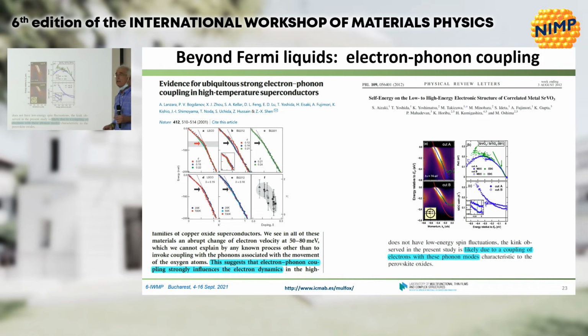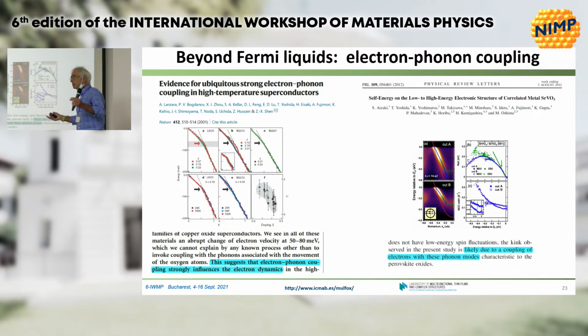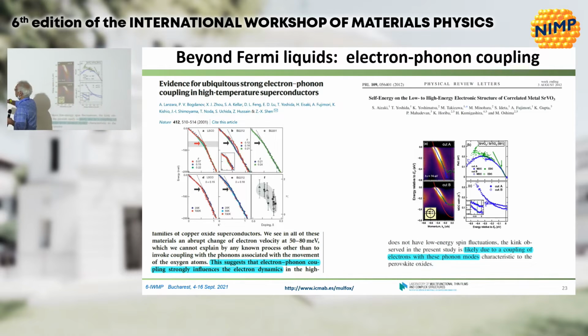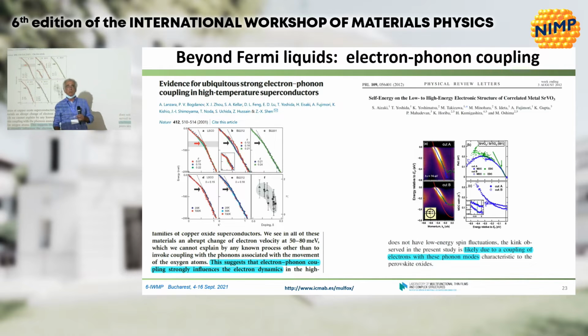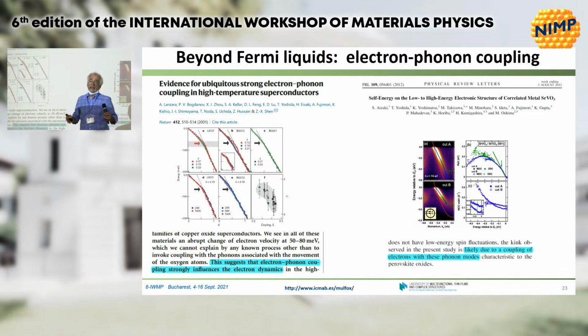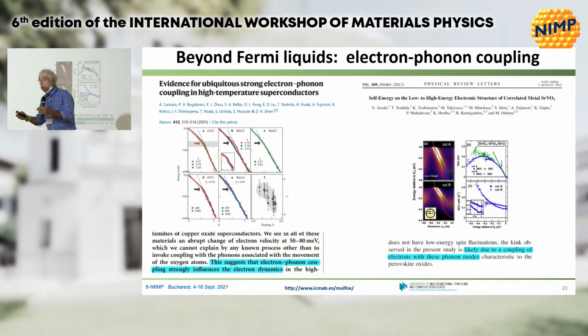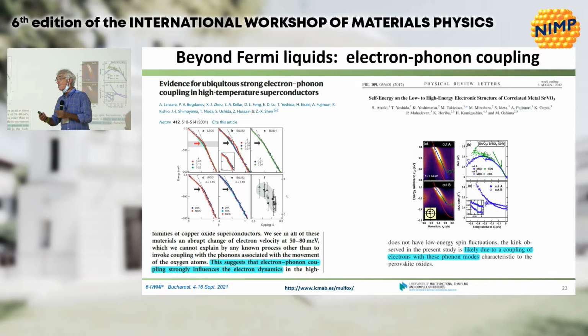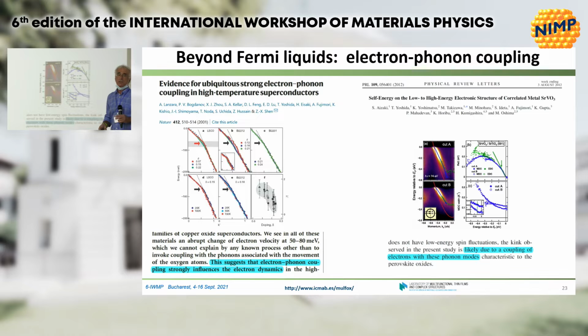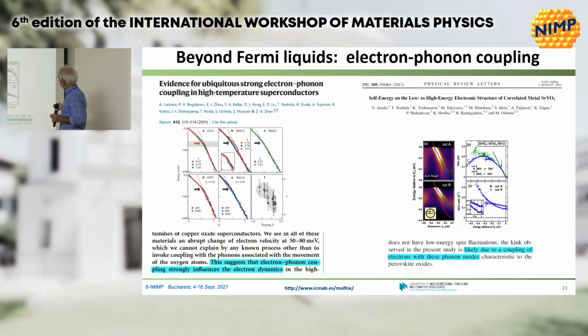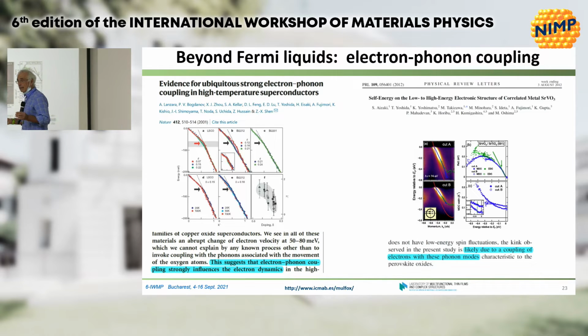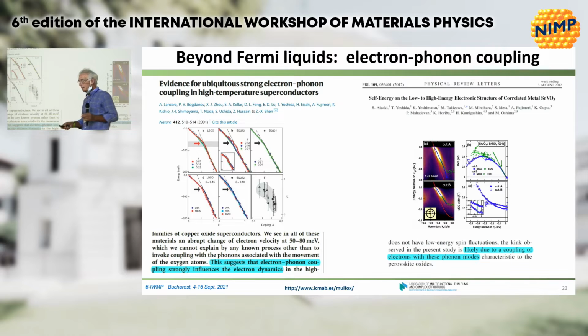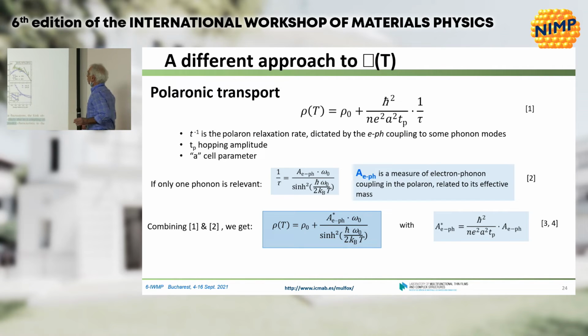There is also spectroscopic evidence of electron-phonon coupling in oxides. This is a very old paper on superconducting materials, the cuprates, and the departure that you see, this is ARPES, this departure from this strange linear behavior is taken as a fingerprint of the presence of some bosons. But in the cuprates you have excitations which are magnetic, so maybe the excitations come from the magnetic aspect of the material. So nobody knows so far the physical origin of this discrepancy. But in vanadates you have this kink here, also taken as a fingerprint of the electrons coupled to some bosons. Vanadates are not magnetic, so maybe here it is just a fingerprint of the coupling to the lattice. So there are some indications, so let's explore that way.